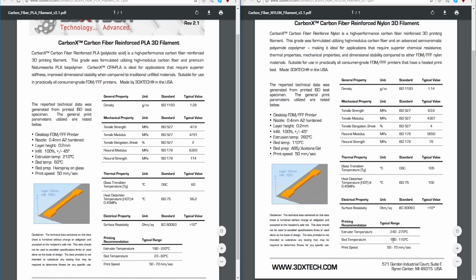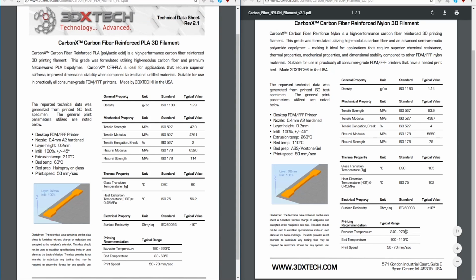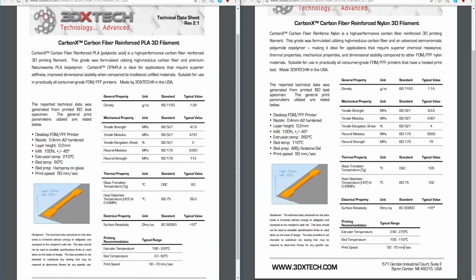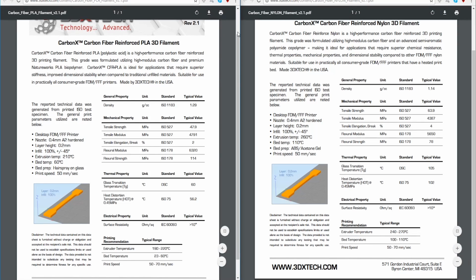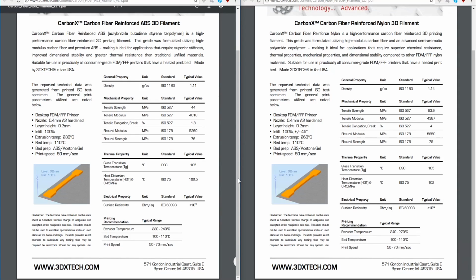This one also needs a heated bed. 240 to 270, so all metal hot end here, otherwise you're going to start melting any inserts you have in there. 100 to 110. Alright, so this is an interesting one because it seems to almost beat out the PLA as far as a selection that I would personally pick. But let's take a look at the ABS compared to it first before we make that consideration.